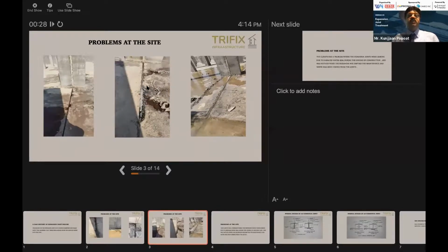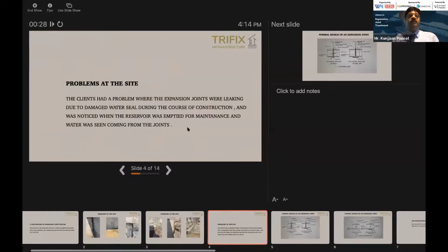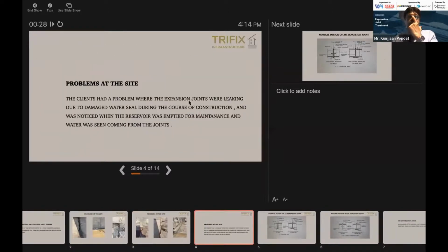These images which you are seeing are after the water was removed from the tank, and it is in a very dry area. The problem at this site was that the expansion joints were leaking due to the damaged water seal during the course of the construction, and was noticed when the reservoir was emptied for maintenance and water was seen coming from the joints.